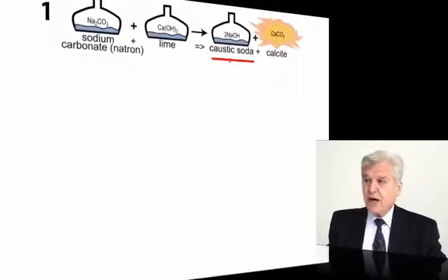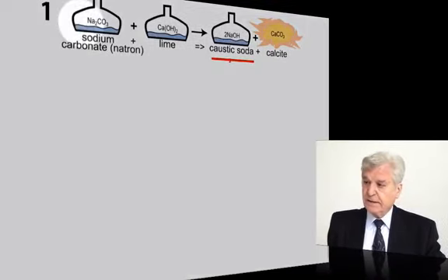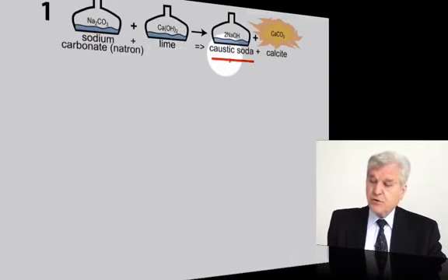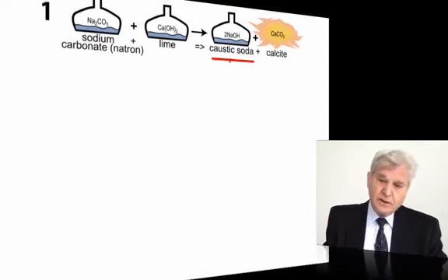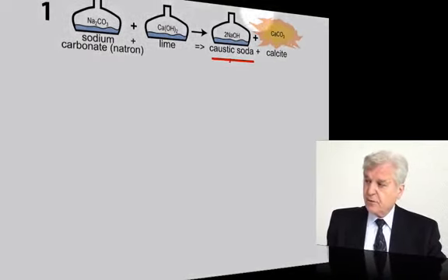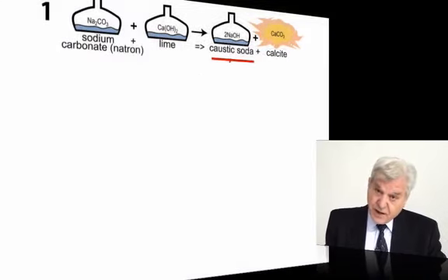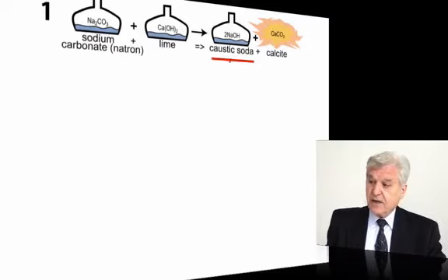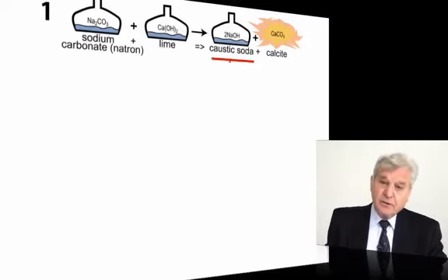And I'll present now the various chemical steps that have been used by the Egyptians in order to make the reagglomerated limestone. These are the steps that are exactly in agreement with the analytical results. The first reaction is the use of sodium carbonate, natron, that reacts with lime, to produce caustic soda. This is the basis of the geopolymeric reaction. And you see that we have also the production of calcite. So you see the first step of using this chemical reaction is the making of a natural mineral, calcite.